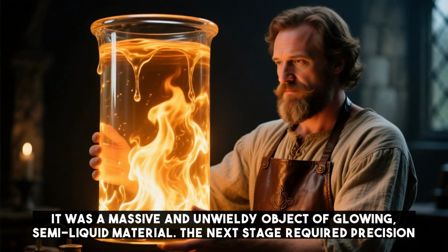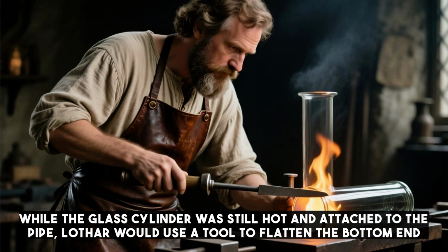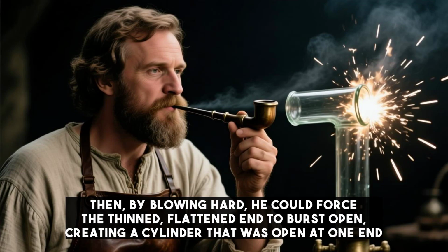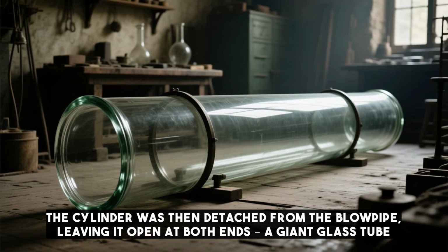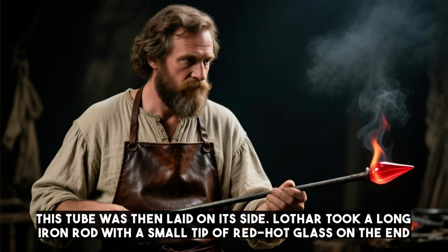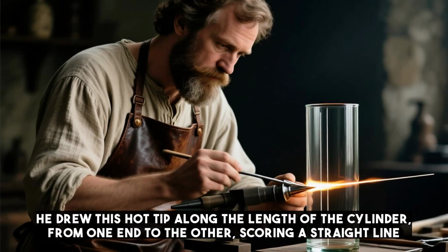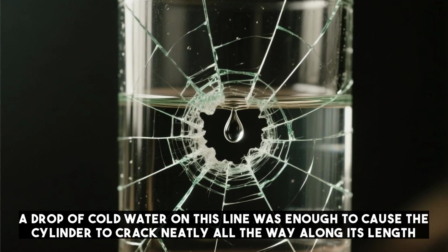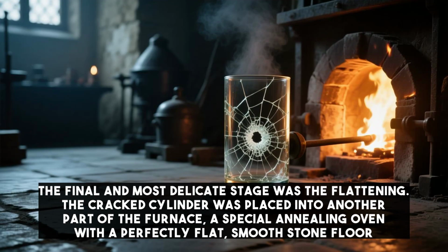The next stage required precision. While the glass cylinder was still hot and attached to the pipe, Lothar would use a tool to flatten the bottom end. Then, by blowing hard, he could force the thinned, flattened end to burst open, creating a cylinder that was open at one end. The cylinder was then detached from the blowpipe, leaving it open at both ends with a giant glass tube. This tube was then laid on its side. Lothar took a long iron rod with a small tip of red-hot glass on the end. He drew this hot tip along the length of the cylinder from one end to the other, scoring a straight line. A drop of cold water on this line was enough to cause the cylinder to crack neatly all the way along its length.